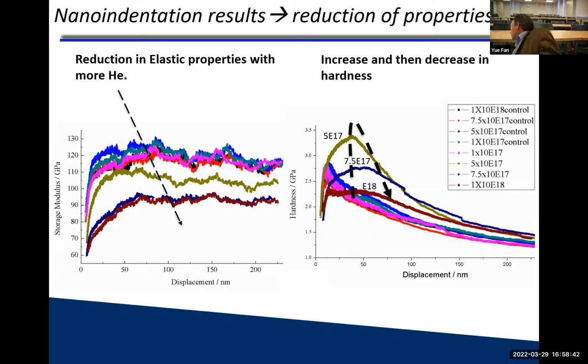However, the hardness, this is hardness unirradiated, but as you irradiate, hardness goes up. But then at higher and higher dose, hardness comes down again. Well, why is that? Well, first it goes up because even though it creates empty space, there are dislocation obstacles and therefore they're hardening. But at some point, you have more empty space than you have solid space, and therefore it becomes weaker as a whole structure at the end because it behaves more like a foam. But interestingly, it never reaches quite the level of unirradiated. So it always stays above, even with this much helium in it. So you do have still some remaining hardening at the end of the day.